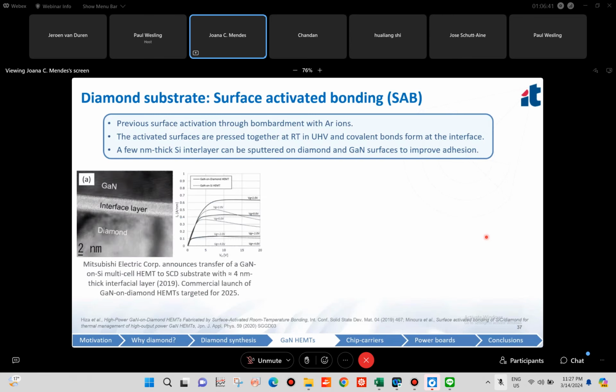And using this method, Mitsubishi Electric in 2019 announced the transfer of a GaN on silicon multi-cell HEMT to a single crystal diamond substrate using a 4 nanometer thick interfacial layer that you can see here. And you can see how the self-heating of the GaN on silicon was really reduced or even eliminated with the